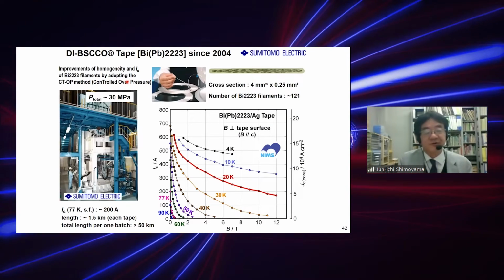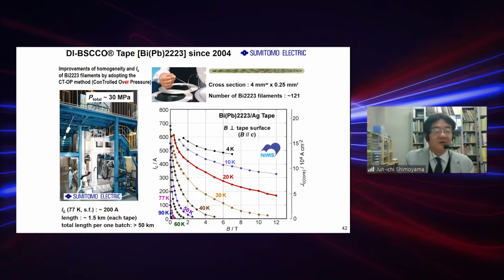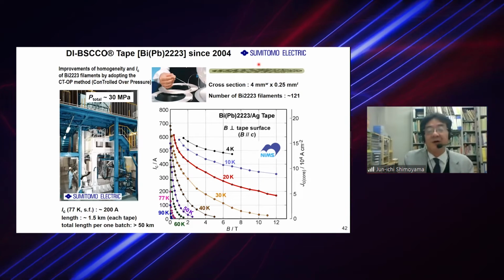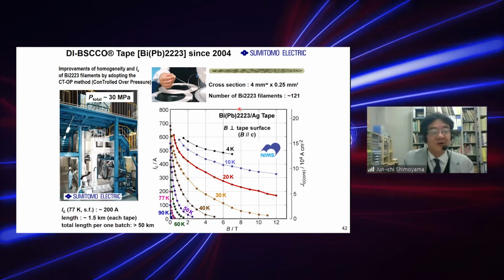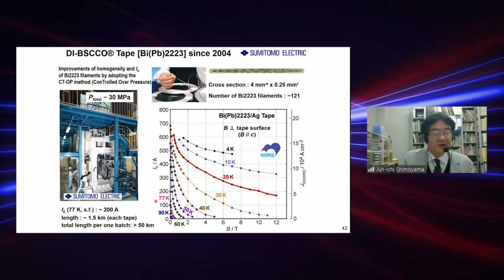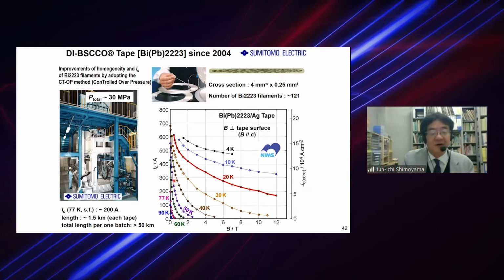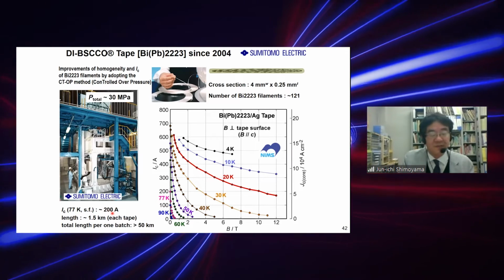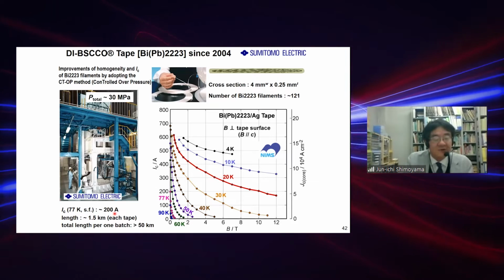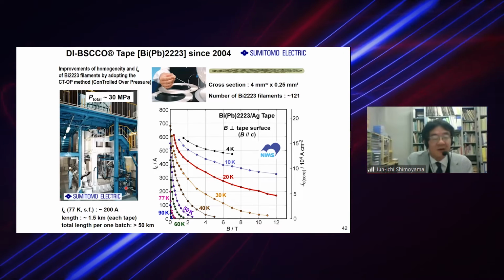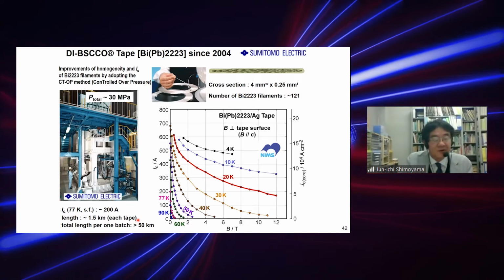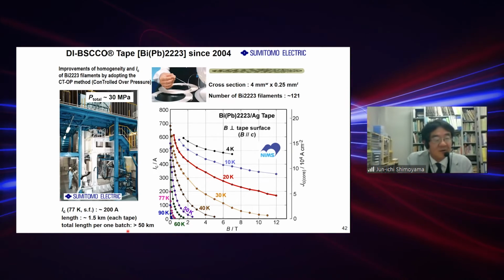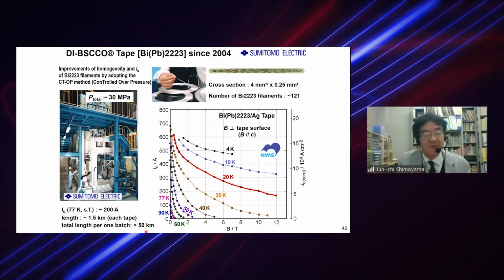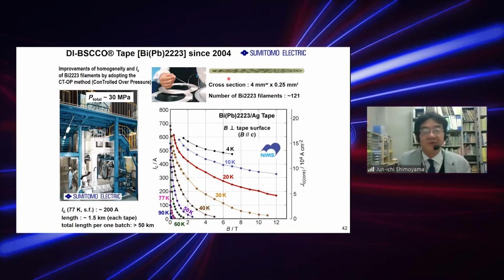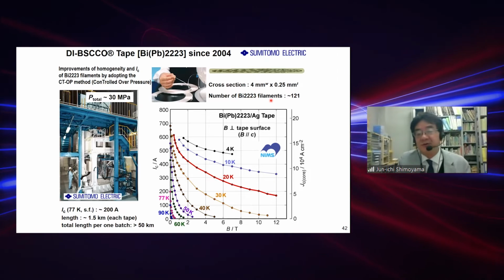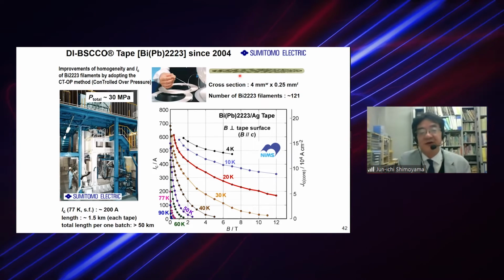So about the BSCCO 2223 tapes, in these 15 years, we mainly use the DI-BSCCO tape developed by Sumitomo Electric company. By using these tapes, we can expect very large critical current up to high temperatures. For example, at 77 Kelvin, critical current is around 200 amps, and the length is very long. And using such big furnaces, we can obtain very long length tapes, in total over 50 kilometers for one batch. But this tape is composed of multi-filament with 121 filaments inside the silver sheath.